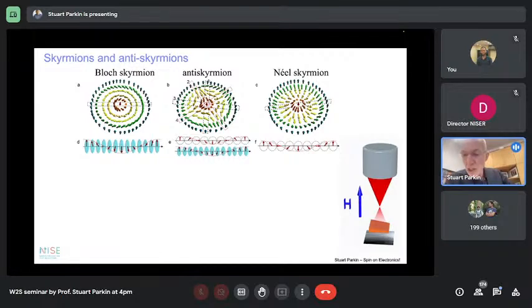And we did this by, when I came to Max Planck, I inherited a very old transmission electron microscope, and we modified it so we could carry out a technique called Lorentz microscopy. What does that mean? That means on the right-hand side, you can see we have a highly focused beam of energetic electrons, 300 kilovolt electrons, and we make then from a single crystalline material, these are materials made by Claudia Felser and her collaborators in Dresden, we make a very thin slice of this material from the single crystal, which is electron transparent.